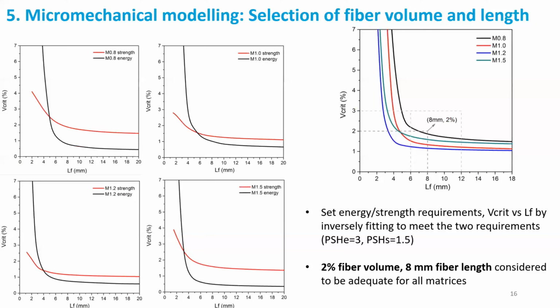As the first step, we're using micromechanical modeling to aid the selection of suitable fiber volume and fiber length. What we do here is that we set the energy and the strength requirements, which are PSH energy equal to 3 and PSH strength equal to 1.5, which are normally used for SHCC materials. We incorporate all the matrix properties and the interface properties tested from the experiments into the model, and we only change the fiber volume and fiber length to meet the two requirements. This is done by inverse fitting, and all the results are shown on the left.